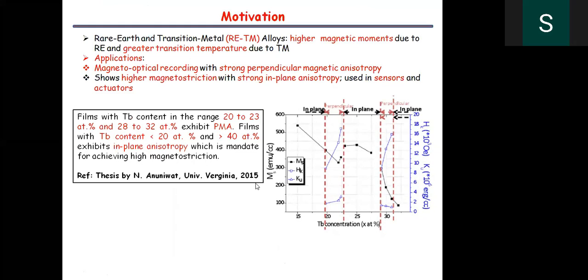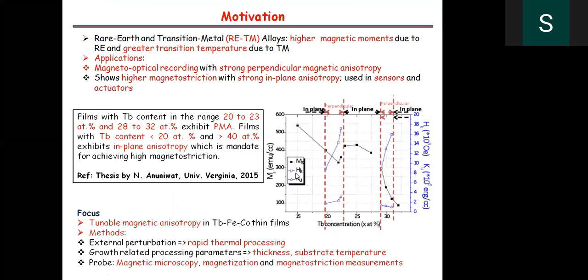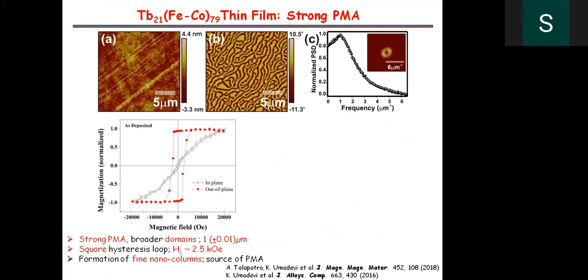As I told you earlier, RE-TM thin films are basically TbFe or TbFeCo based thin films, and they show a rich phase diagram. The phase diagram showed that the material has in-plane and out-of-plane magnetic anisotropies based on the Tb to FeCo ratio. So we wanted to establish the phase equilibrium and generate a magnetic phase diagram. We took films with different compositions and tried to see the magnetic properties using magnetic microscopic techniques, particularly a magneto-optic microscopic study correlated with magnetization studies.